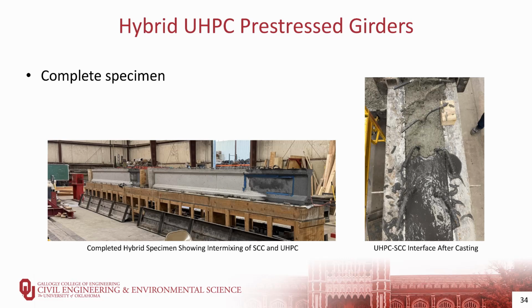There's also the possibility for different densities between the materials, and so one is pushing harder on the other. We've even talked with some of our chemical engineering colleagues about how we might be able to model that fluid flow to better quantify these flow rates. But it is something that takes some work to get right. Just adding to that, you can see from the other beam, which we cast after the first one, that the SCC did not really flow as much into the UHPC end region like the one we see.